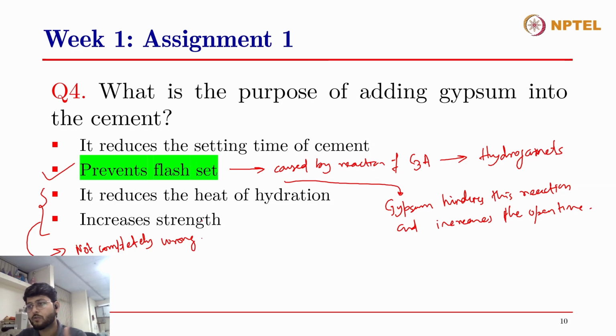So sometimes adding gypsum increases the strength as well, because ettringite is a denser material than hydrogarnets, and that leads to taking up a lower amount of volume, and with the continued formation of ettringite throughout the life of the structure or the cement or concrete, it increases the strength. So these last two statements are not completely wrong. Gypsum could increase the strength a little bit, and it also could reduce the heat of hydration by a factor.